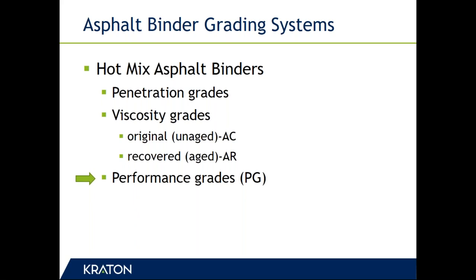And so that evolved into penetration grades, which is another ASTM designation that came along very early. I believe that's D5. What that did is take a standard Singer sewing needle and use that to penetrate for 5 seconds with a 100 gram weight. And the amount that it penetrated at room temperature was the way that asphalt binders were graded for a long time and continued to be graded around the world in many other countries.